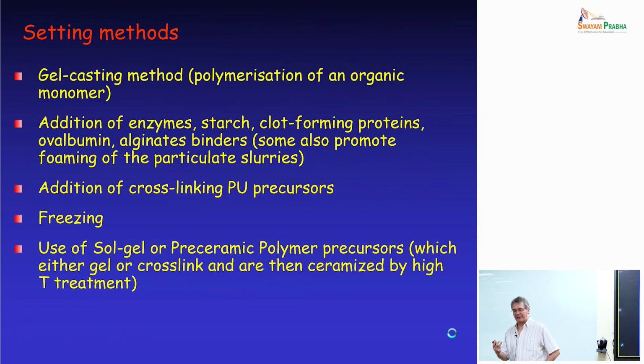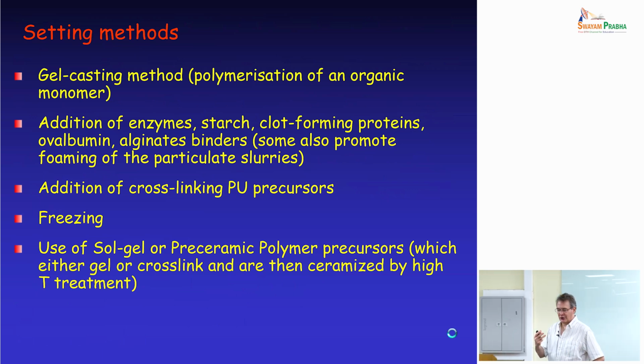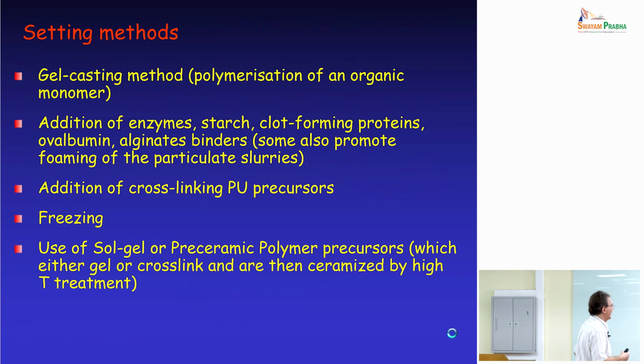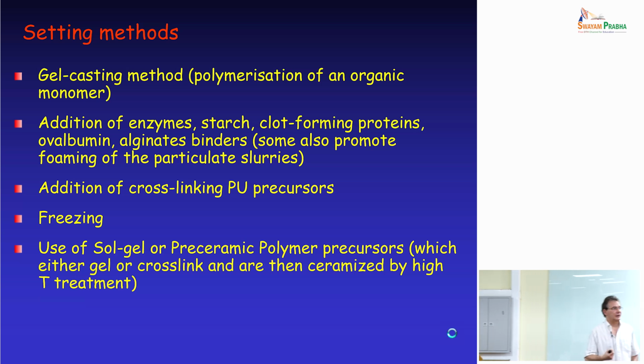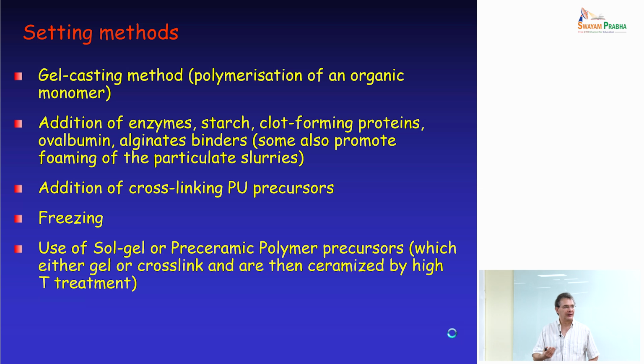So once you have made this liquid suspension embedding gas, so you made your slurry-based foam, you need to consolidate, you need to set the foam, and you can use gel casting. So you can add an organic monomer into the system that can polymerize, or people have been using all sorts of binders that are water soluble, for instance, starch or different proteins that consolidate the liquid.